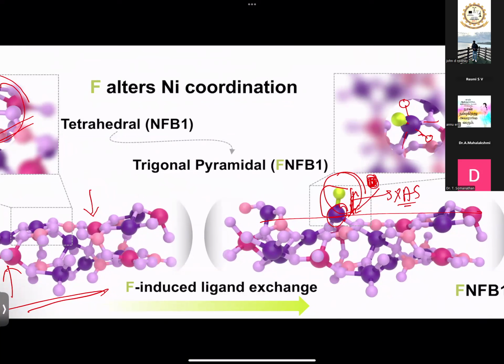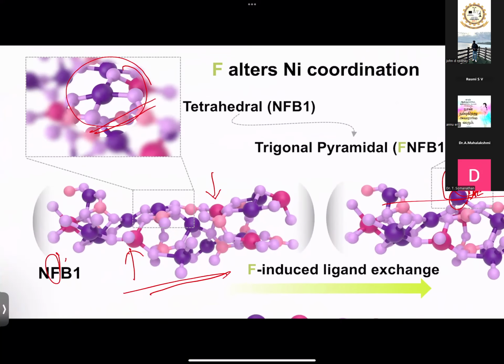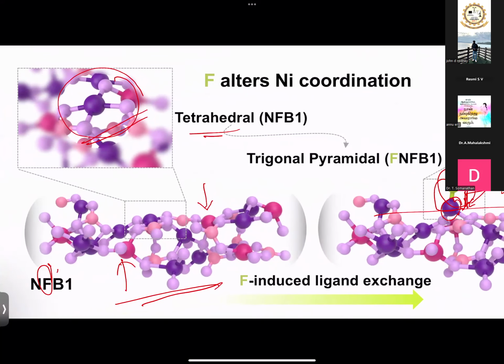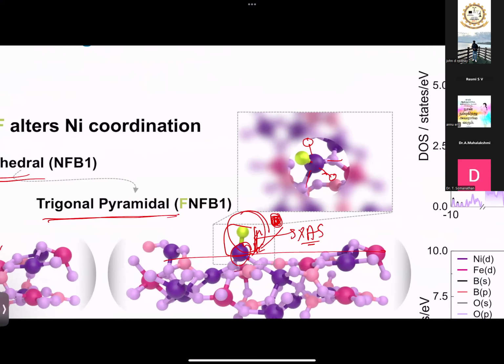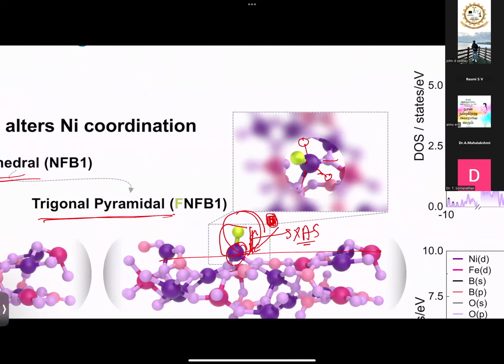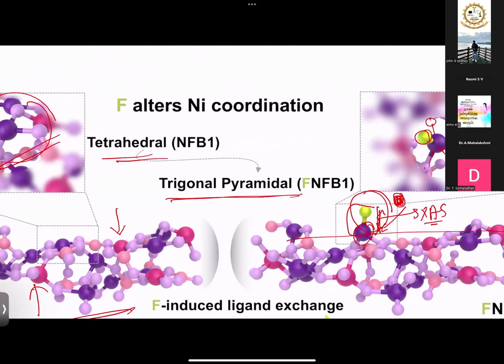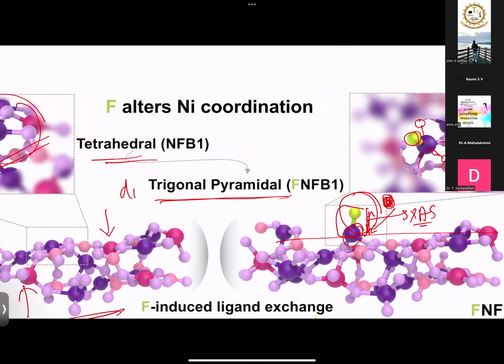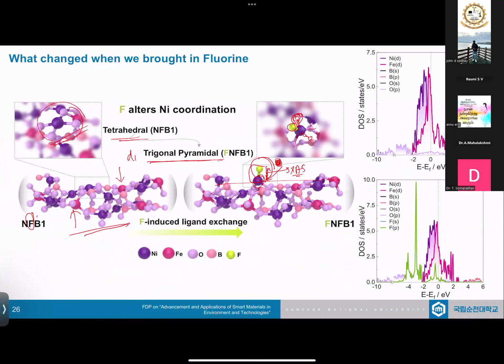Again, we saw in XAS that this might have happened, which is proved through DFT, that the tetrahedral nature is gone and changed to not a perfect trigonal pyramidal nature, because a perfect trigonal pyramidal has to have 3 oxygen atoms with an atom on the top, whereas this is a distorted trigonal where you have a vacancy. As you saw in XPS, there is an oxygen vacancy present in the system, which will actually alter our mechanism, as we will see. These are the DOS studies. I'm not going into it because I'm losing my time over here.